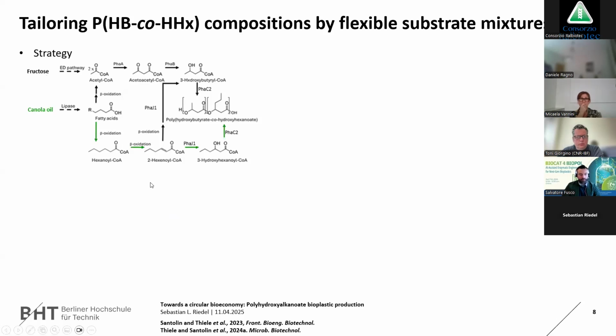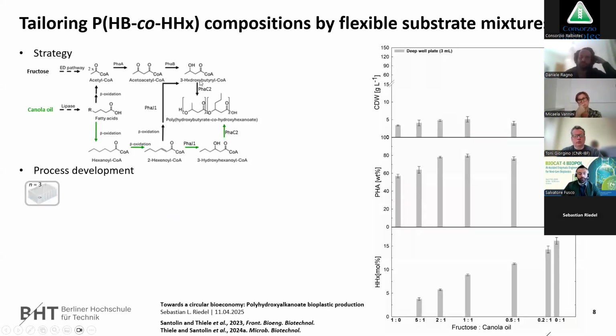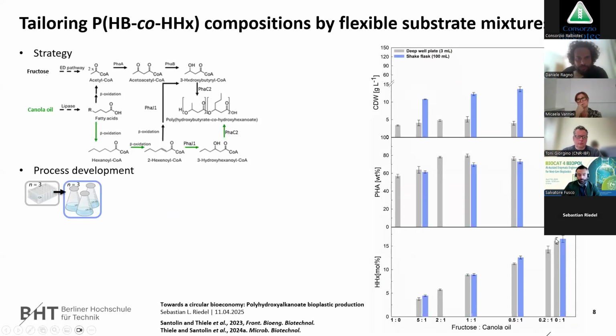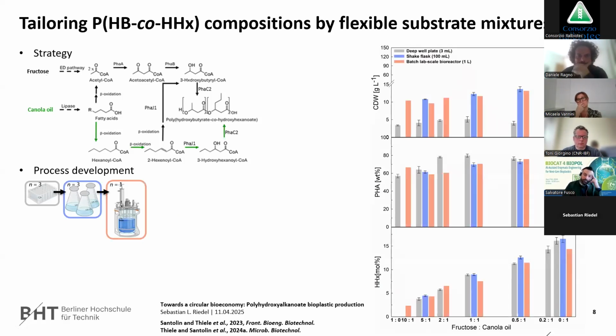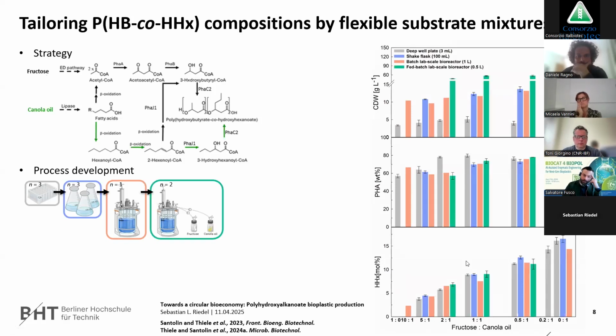So one project we had was to tailor the content of the copolymer. And so, as I said, our strain needs lipids to make these HHX. We did this by controlling the mixture of sugar and oil. So with sugar, you only get HB. We started in small scale, and then on the bottom you see that we were able to go from 0 to here 17 mole%, and this was transferred to a bigger batch reactor even, and then we started also to do this in fed batch to get this amount of 60 gram per liter, and we're still able to get this controlled composition.